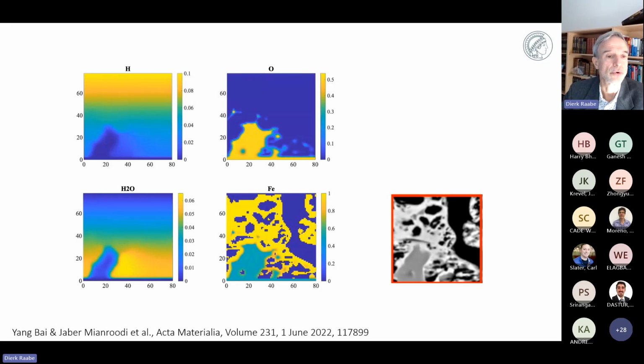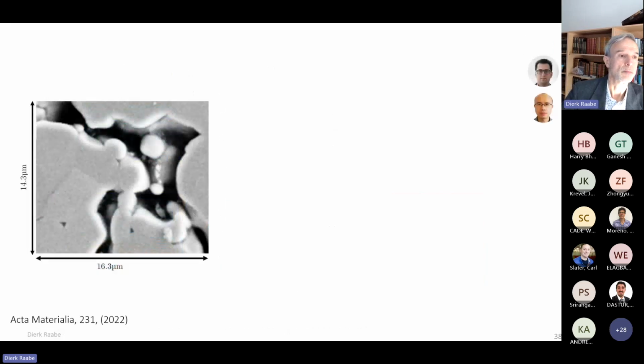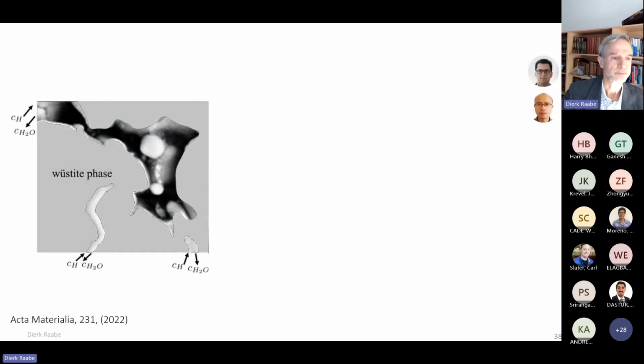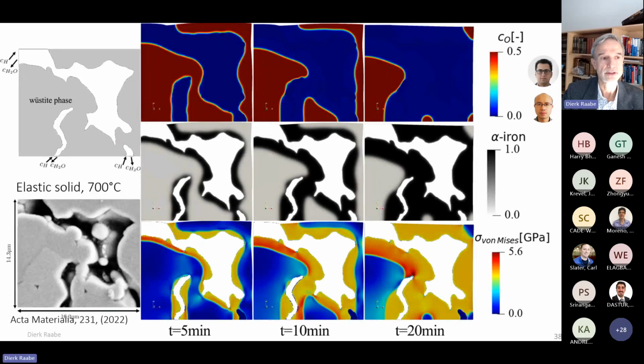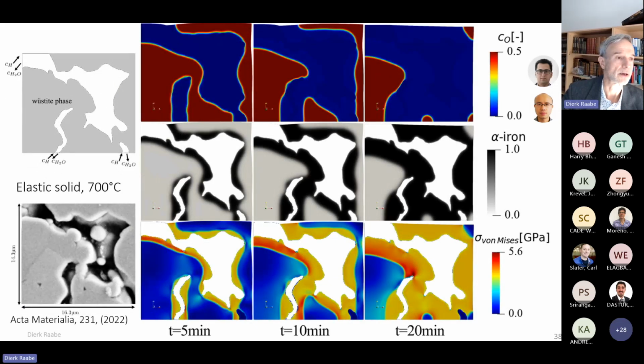And then you can also, for very heterogeneous scenarios, predict where the iron is formed, and you see substantial deviations from the classical core shell models. But as I said already, we also have to account for elastic stresses. That is something where the classical models do not include this effect. And here we did a couple of phase field calculations where we started just in a pure elastic version. And we made our life in the beginning very simple by translating the loss of oxygen to a corresponding displacement field from which you can calculate the displacement gradient, which in turn, when you feed that into Hooke's law, gives you an elastic stress.